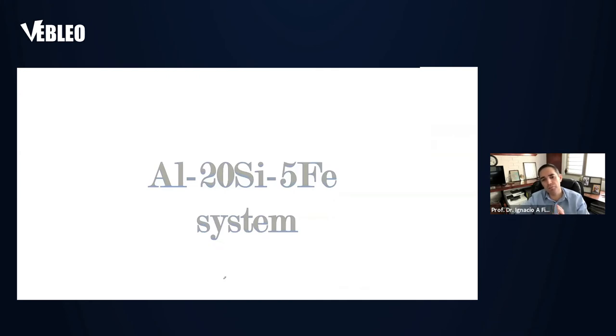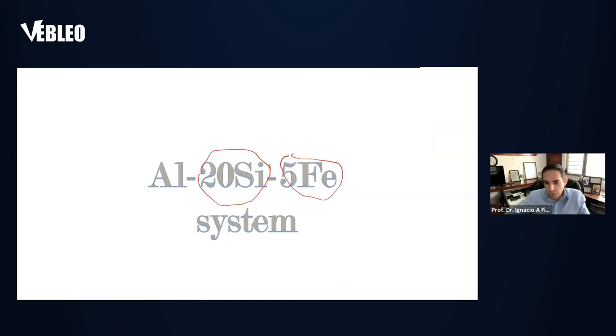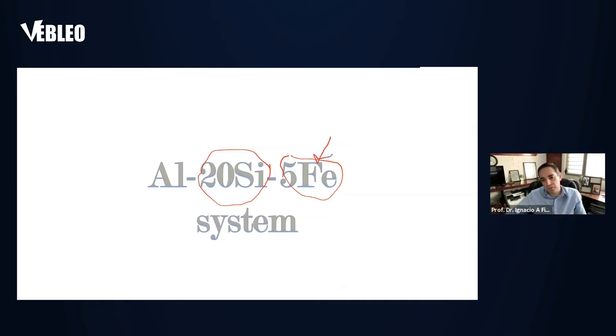We're going to start to talk about the master alloy systems. As you can see here, we're using quite a lot of silicon in the alloy and 5% of iron. Why 5% of iron? Because it's considered an impurity in this kind of alloys and we wanted to move to the very upper limit of the system. If we studied this one and could improve the mechanical properties, with less iron we'd expect to have even better properties.